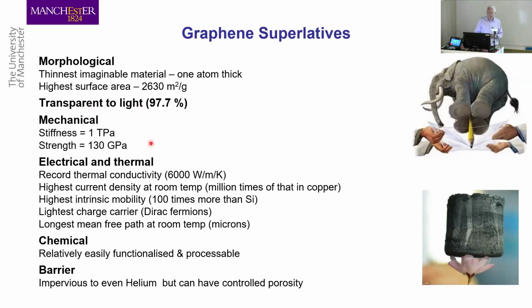Of particular interest to me is the stiffness. It has a mechanical stiffness of 1 terapascal, 1,000 gigapascals, 4 times stiffer than steel. And we have strength estimated at 130 gigapascals, which is the most enormous level of strength. And that's something I want to talk about a little bit. But there's also other properties: record high thermal conductivity, very high electron mobility, carriers going around relativistically. A lot of physics can be done.